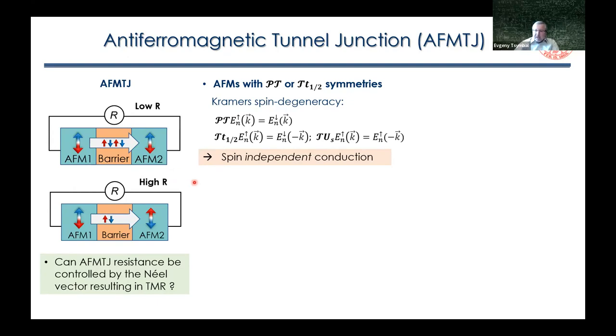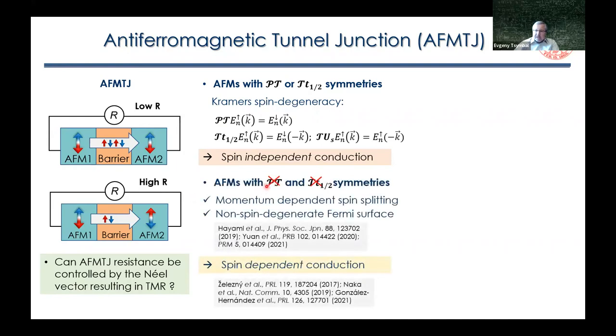So it appeared, however, that in certain types of antiferromagnets, these symmetries may be broken. And in this case, it's not forbidden to have a band structure with momentum-dependent spin splitting in this kind of antiferromagnets. And as a result, we should have non-spin-degenerate Fermi surfaces. As a reference, you can look at these publications where this idea was introduced. So as a result, it was argued that the presence of non-degenerate spin Fermi surfaces can lead to spin-dependent conduction.